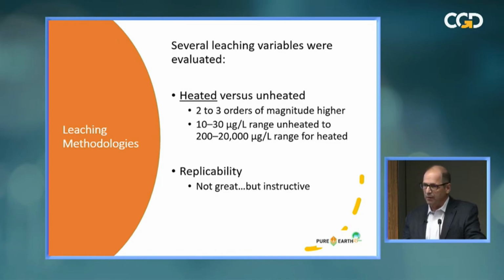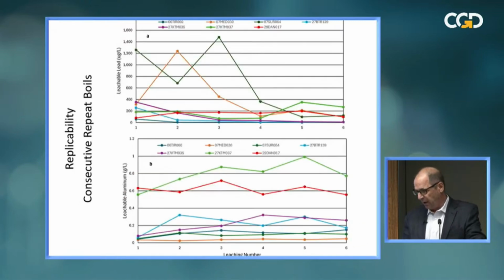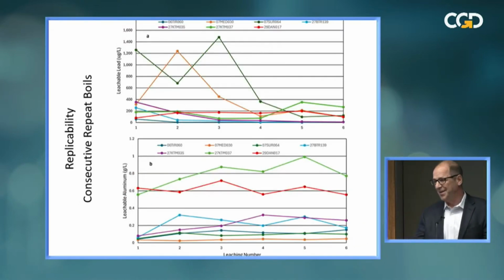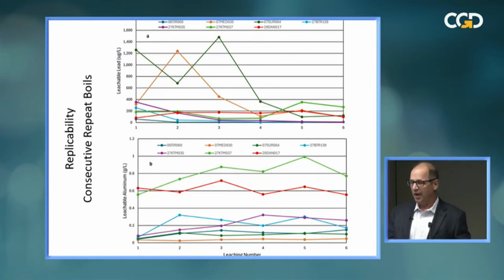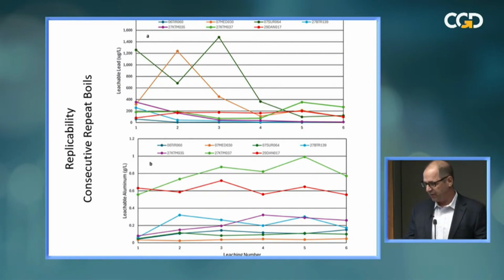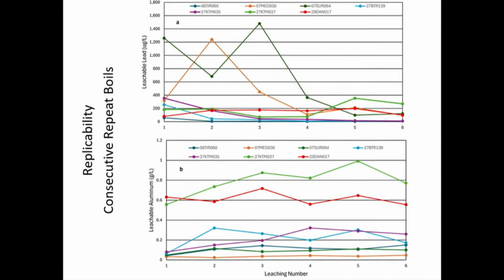Replicability we also looked at, like can you take the same pot and leach it repeatedly and get the same results? It's an important research question and an interpretation question as well. And we found out that no, you can't. You leach the same pot over and over again. We did 7 pots 6 times. We found that the lead levels were quite variable as we went, generally decreasing. Sometimes they went up and sometimes they went down. Meanwhile, the aluminum concentrations, also extremely high, were way more consistent over time. And we'll get back to this later.